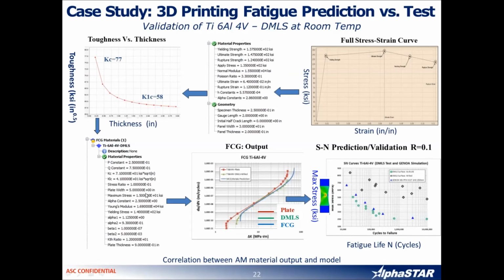So all this process is done using MCQ Metal software. Once this curve is available, we can take this information inside an actual FEM coupon simulation here, and we can predict the SN curve here as shown in the bottom right for the R equal to 0.1 case. The triangle ones are predicted using GENOA, which is a simulation, and the circle ones are given from test, and it shows a pretty good comparison right here. So the correlation between the AM material output and models is clearly shown here.